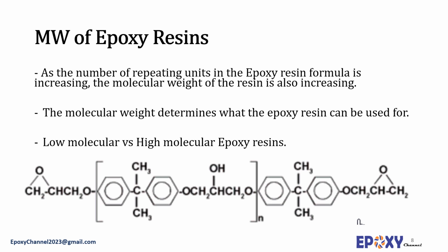For example, epoxy resins with two epoxy groups in each molecule, like the one shown here, with an average molecular weight of 382, would have an EEW of 191, which means 382 divided by 2. So if you know the number of epoxy rings per molecule and the molecular weight, you simply can calculate the EEW and estimate the amount of the required hardener or curing agents.